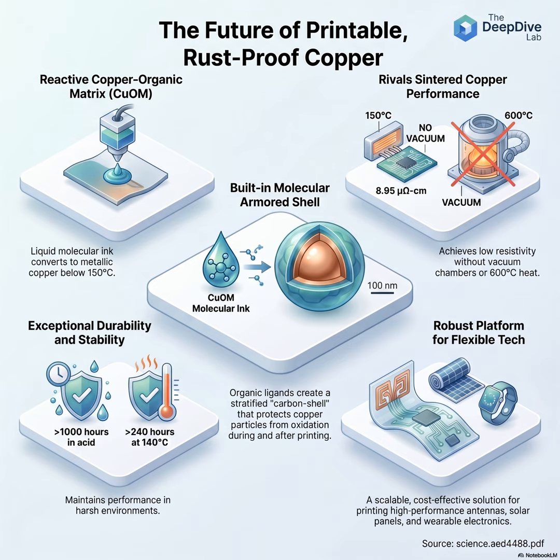Let's talk about that data, because imagine leaving a delicate circuit board in an acid bath for a month and a half, and it still works perfectly. Which sounds impossible. Right. If you were to drop the motherboard of your current laptop into a bath of harsh industrial acid, the copper wiring would dissolve almost immediately. Instantly. But the researchers took their low-temperature printed copper and submerged it in harsh acid. And it survived, remaining fully functional and highly conductive for over 1,000 hours. Over 1,000 hours. They also subjected it to a highly corrosive sulfide environment. Like the kind of conditions you might find in heavy industrial plants or deep-sea equipment. Exactly. And it lasted over 200 hours without degrading. Wow. They even baked it in an oven at 140 degrees Celsius for 240 hours. Yeah. And the carbon armor held perfectly.